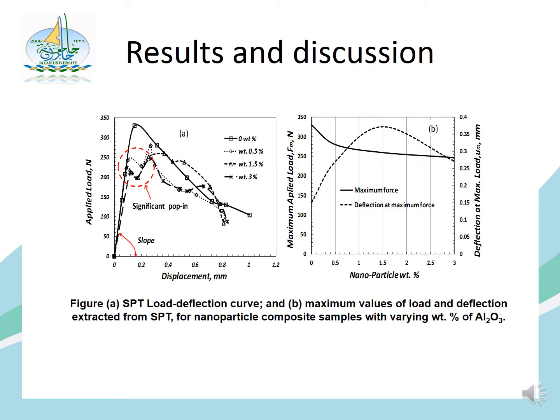Okay, here I'm trying to show you what we have done in the small punch test for this study. In this figure, we are showing the experimental small punch test deflection curve, shown here on the left in A, the load versus the displacement, and we can see the materials with no additive, 0.5 percent, 1.5 and 3 percent additive. In these curves we can see how the behavior should look, starting from the top one here, and the other one shows how it behaves.